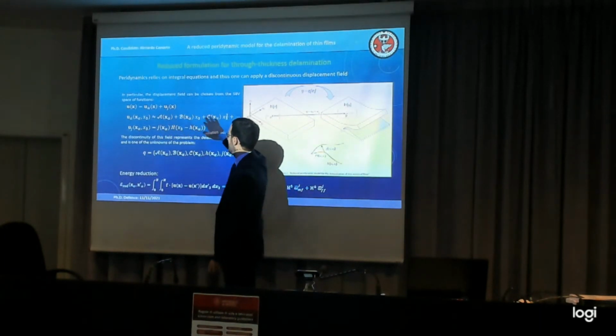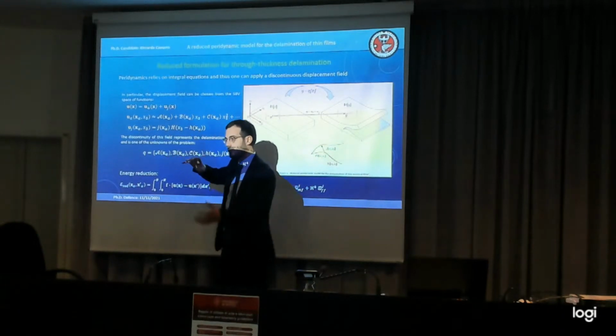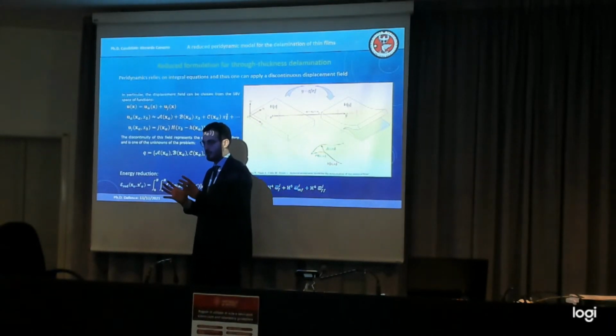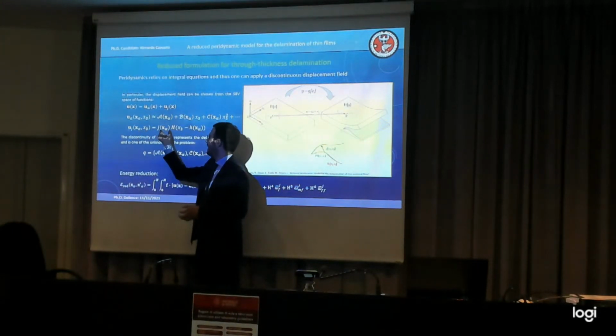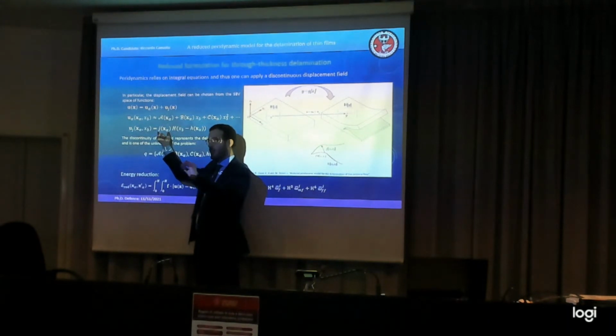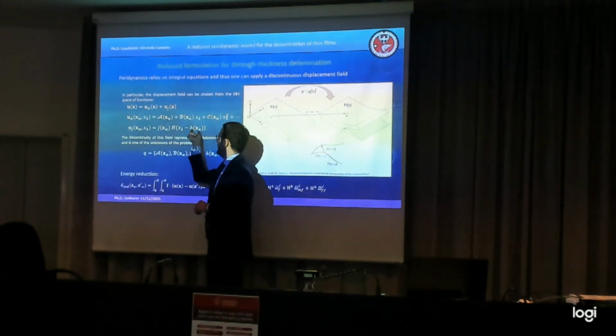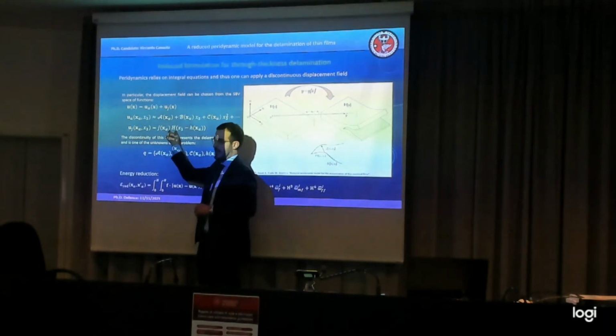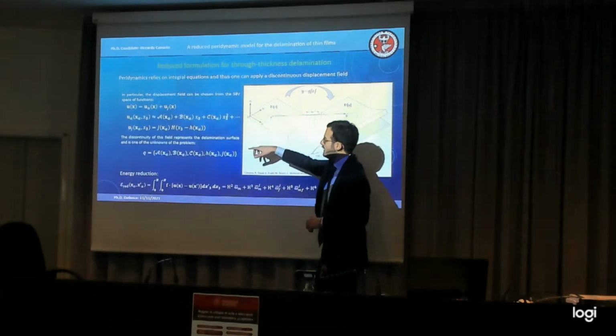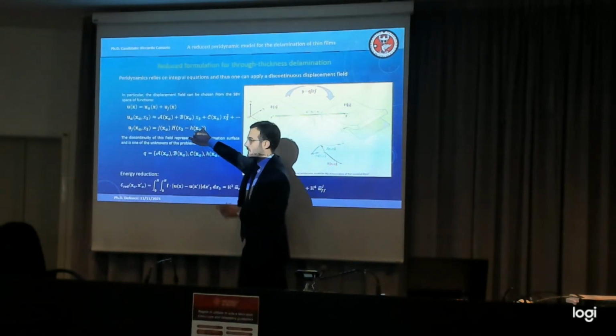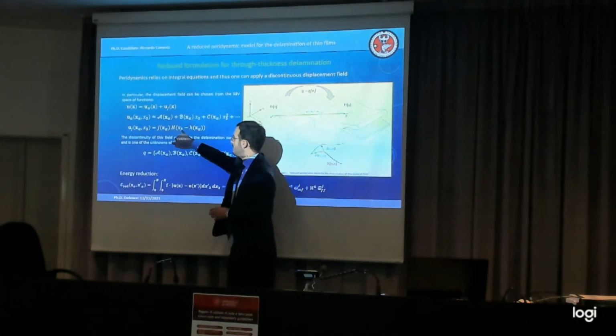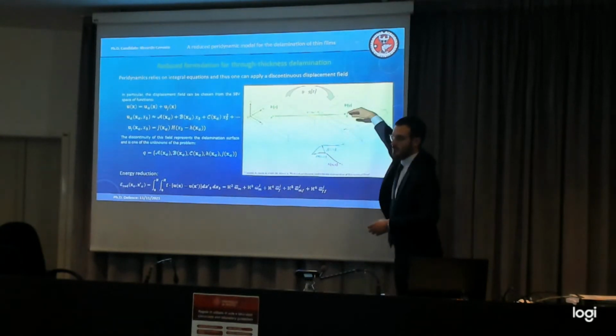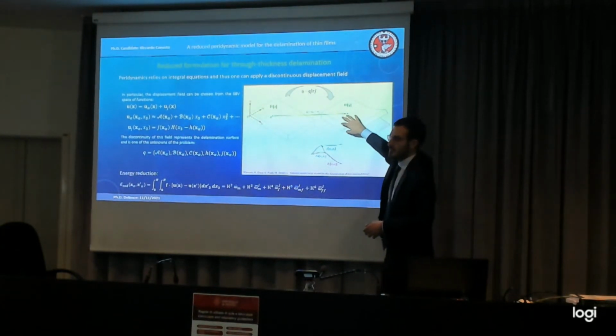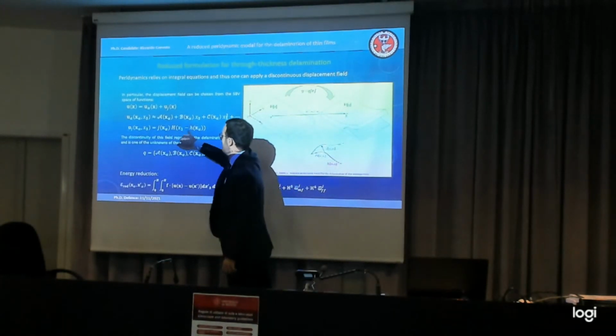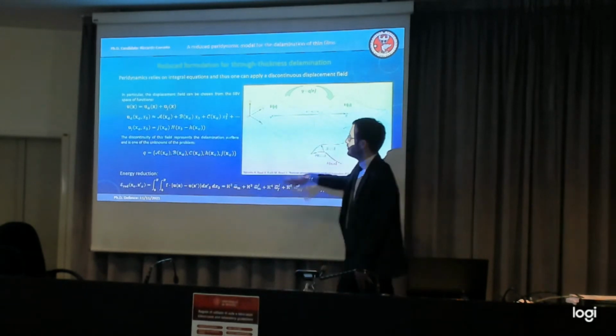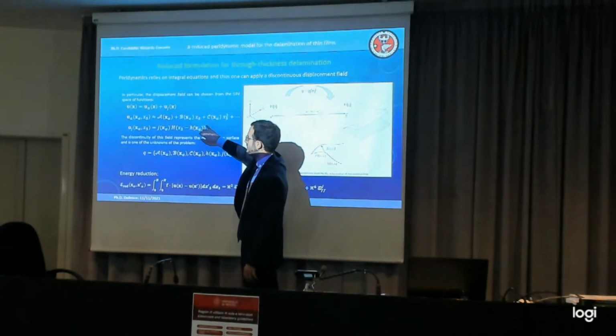So this is the way that we treated the continuous part, and the jump part. We wanted to keep it as general as possible, and so the jump is composed of a jump function. This gives how much the point will jump in the new configuration, and a delamination function, which is put inside a Heaviside function that is localizing the jump. When I say localize, it's to pinpoint all the parts of the body that will go through a jump. So there is something that is not jumping and something that is jumping, and it is identified by this function over here, which depends on the delamination function. Then when you do these two ansatzes, this is the most general way possible.